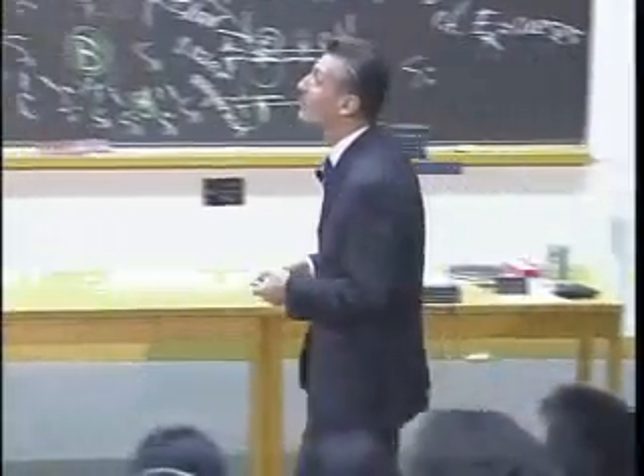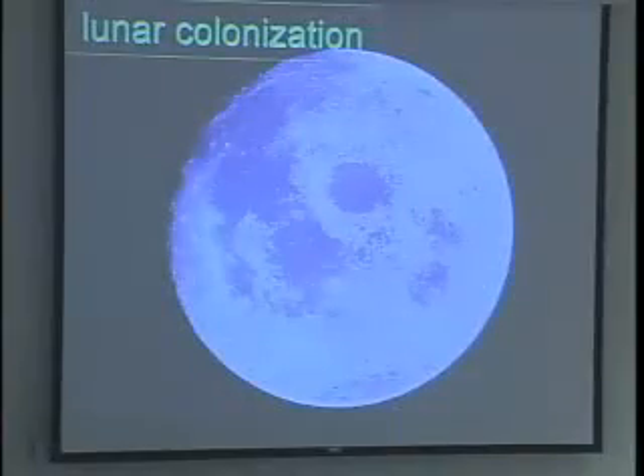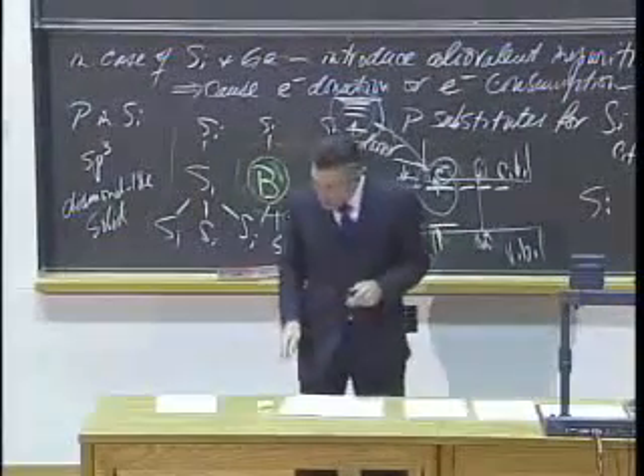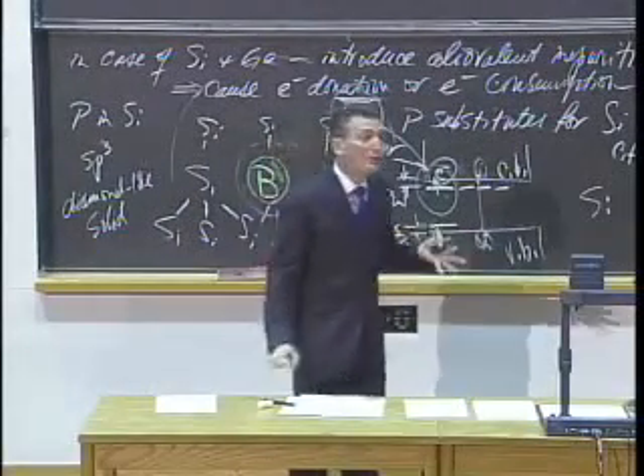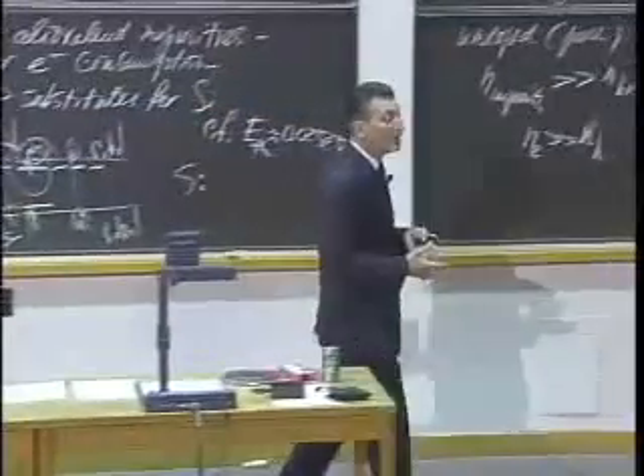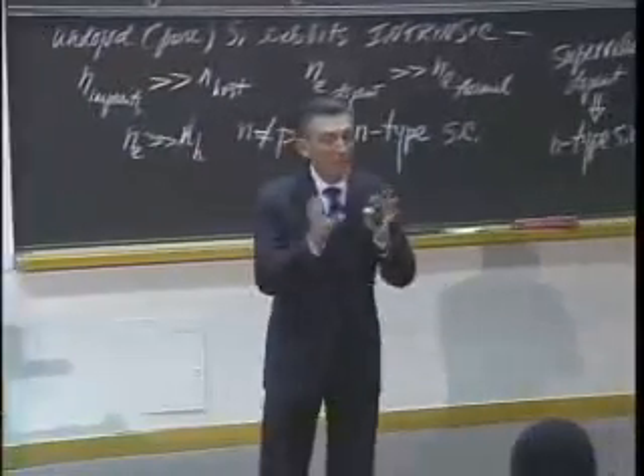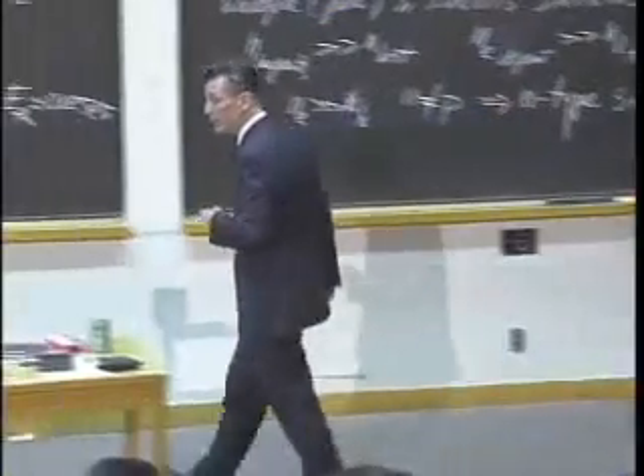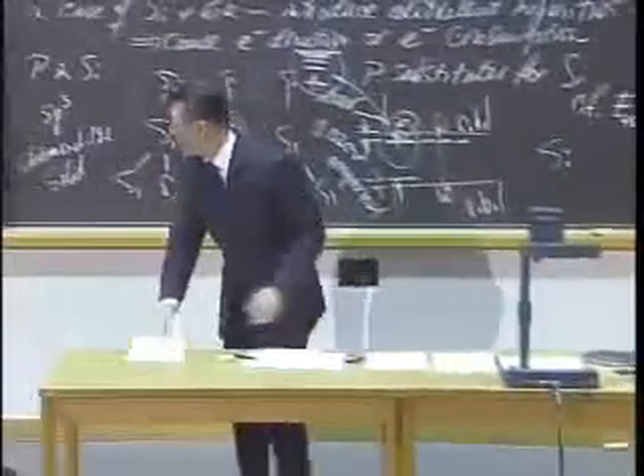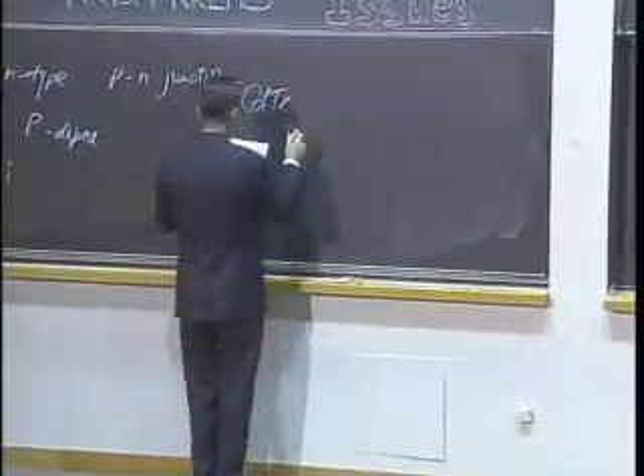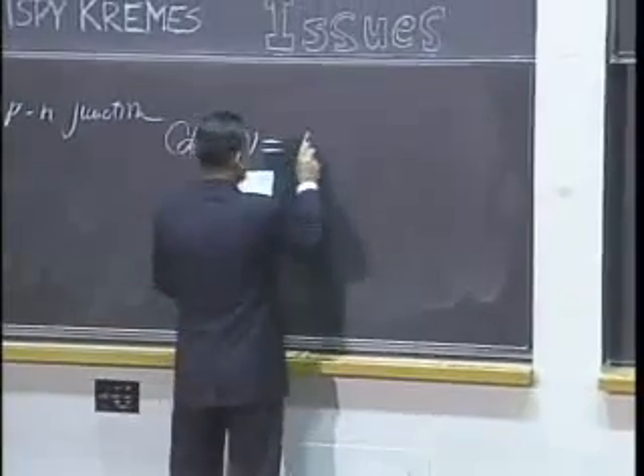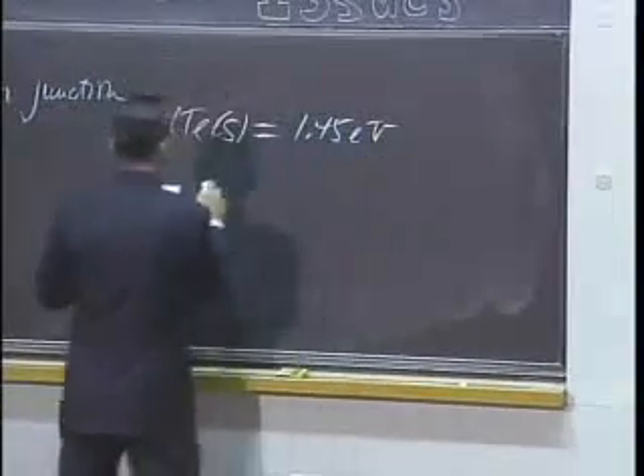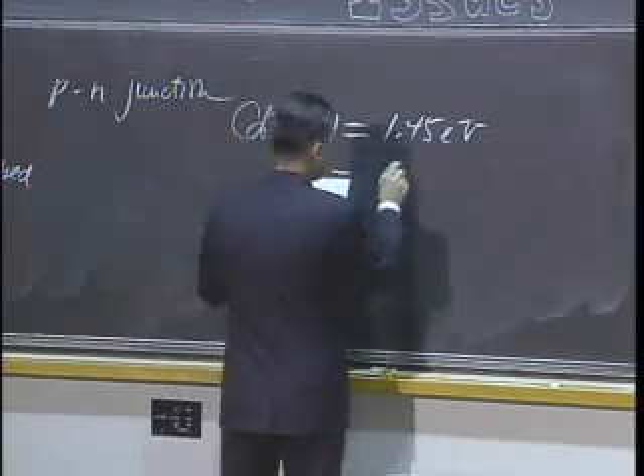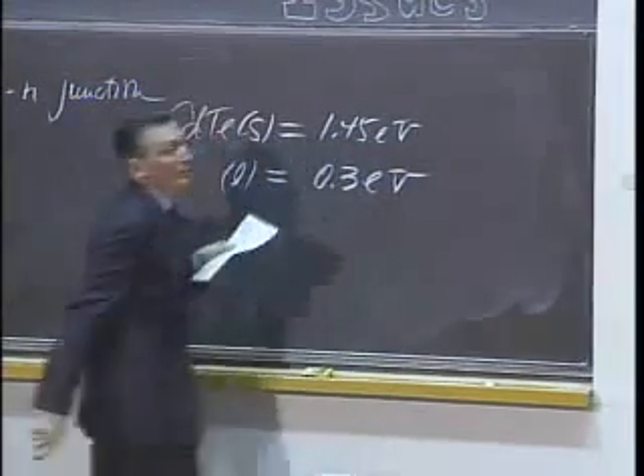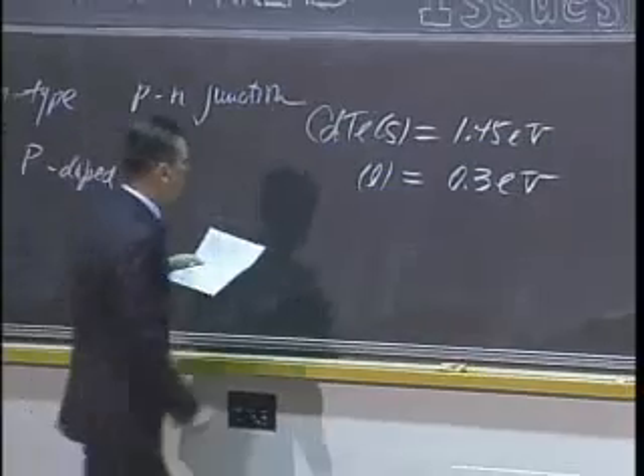Think about that sometime. Now, the last thing I want to tell you is that not only do you have solid semiconductors, you have liquid semiconductors. And when silicon melts, it's not a semiconductor. Silicon melts, the band gap collapses, and molten silicon behaves as a liquid metal. But for example, something like cadmium telluride, which is useful in night vision, cadmium telluride as a solid has a band gap on the order of 1.45 electron volts. As a liquid, it still has a band gap. It's about 0.3 electron volts. So it is parked down in the infrared.